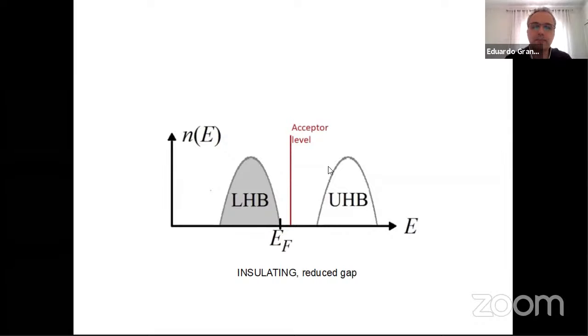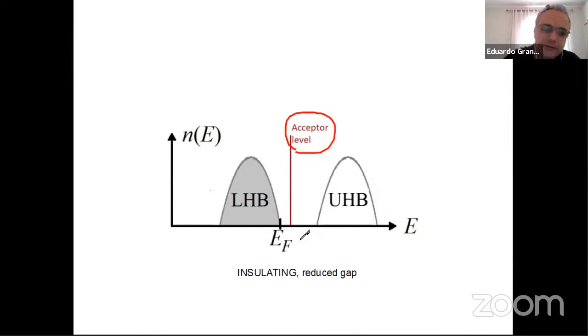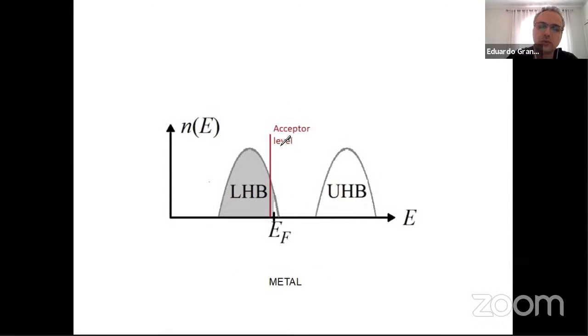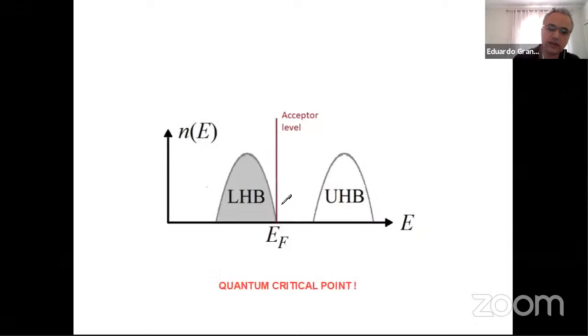So you may induce an impurity level. Inspired by semiconductor physics, you may have this acceptor level, which, if you are lucky or smart enough, could be very close to the Fermi energy. So for some substitutions, you may expect the acceptor level slightly above the Fermi energy. That will lead to an insulating material because you don't actually close the gap. We just reduce the gap, like in a semiconductor, right? On the other hand, you may perform another substitution where the acceptor level falls below the Fermi energy. So in that case, in principle, you are able to induce holes in the valence band, and because of that, you may have some levels in the valence band which are empty, and in this case, you may induce a metallic phase, and that's a way to go through a metal-insulator transition.